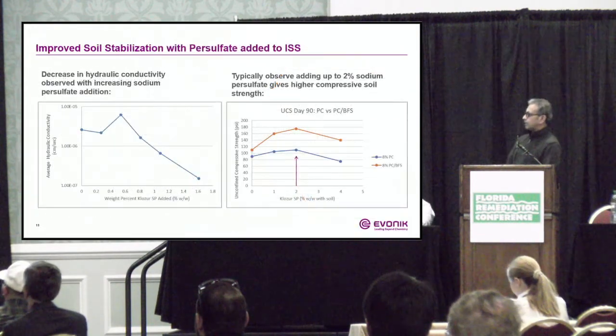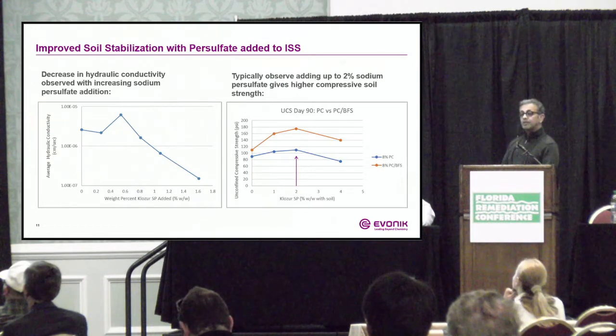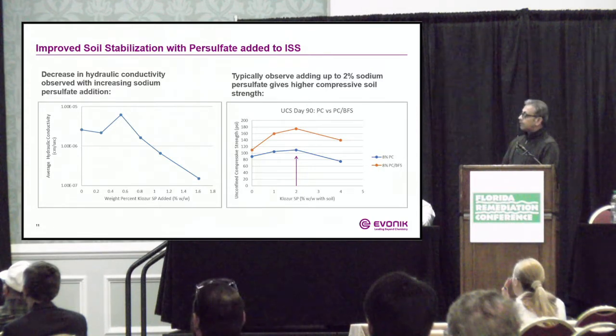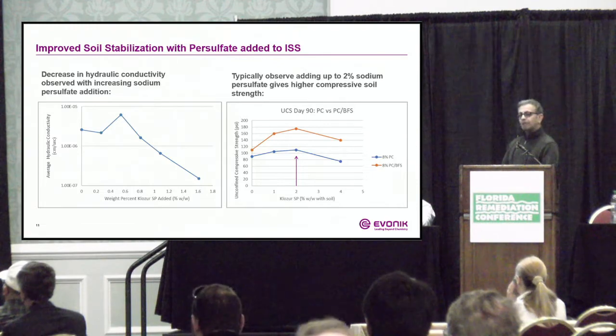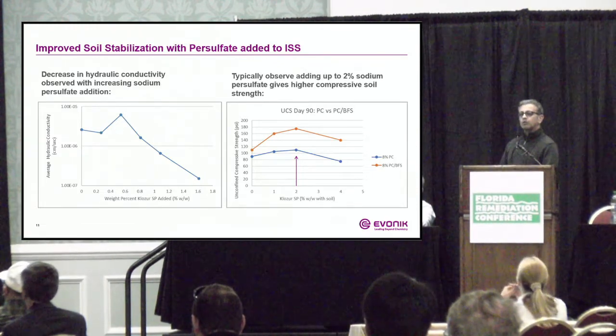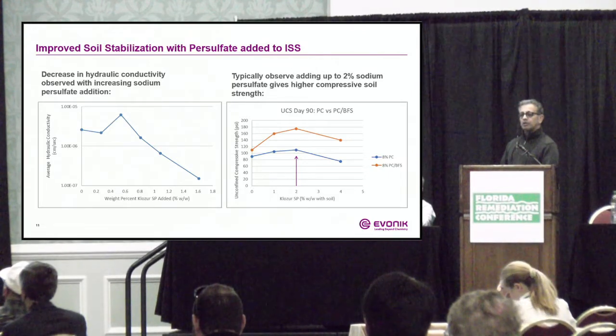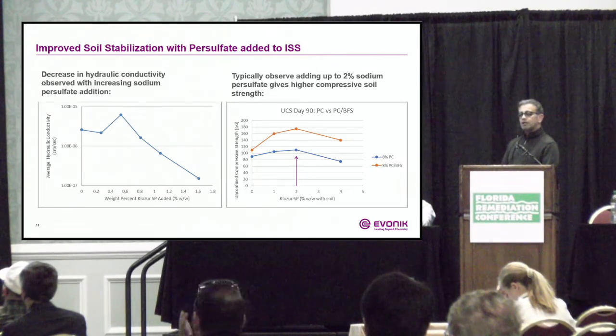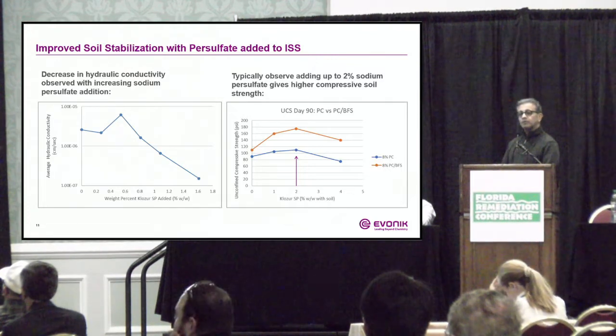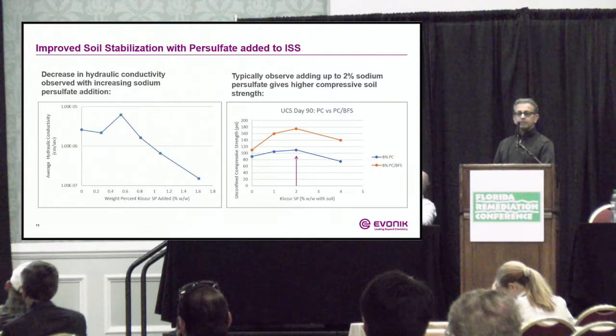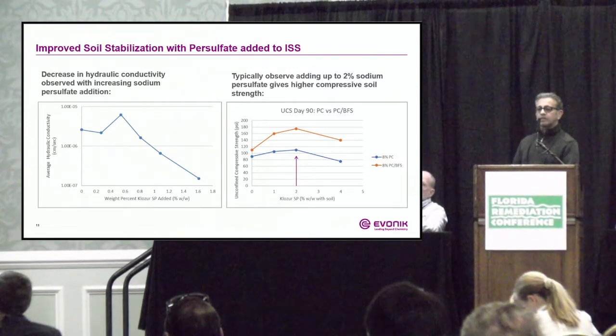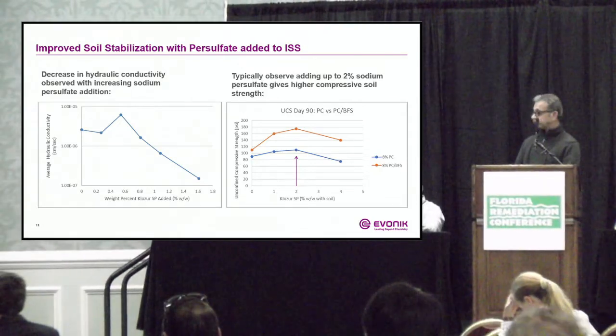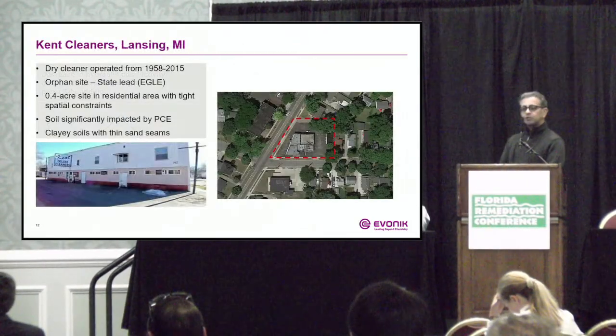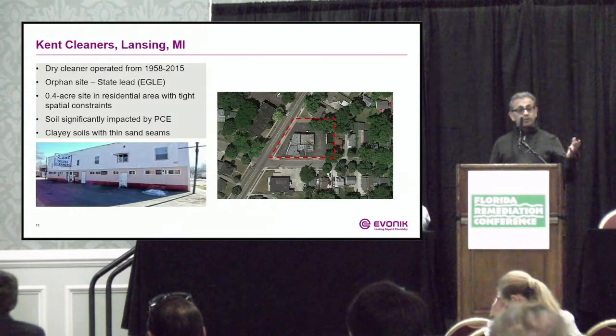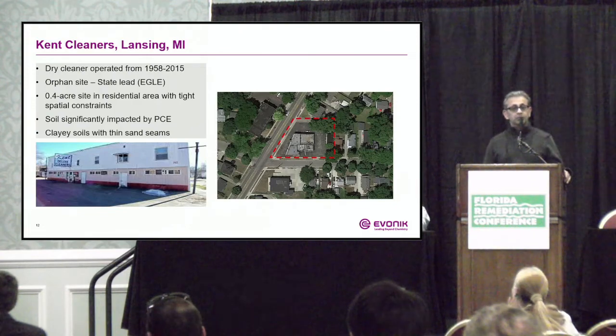He also demonstrated in the study that adding small amounts of persulfate decreases the hydraulic conductivity. That can be seen in the chart on the left. By adding about 1 to 1.5% of sodium persulfate, you can get one order of magnitude reduction in the hydraulic conductivity. And they also demonstrated on the right that by adding small amounts of persulfate, the unconfined compressive strength of the soil also increases. So if you add about 2% persulfate, it increases the unconfined compressive strength. Okay, so that was the background on what ISCO is, what ISS is, and what the benefits are of combining the two technologies together.